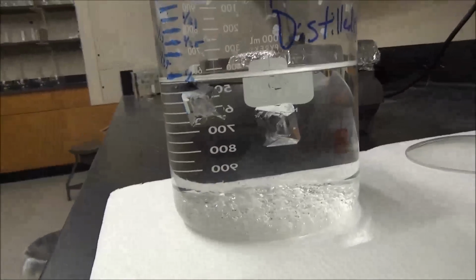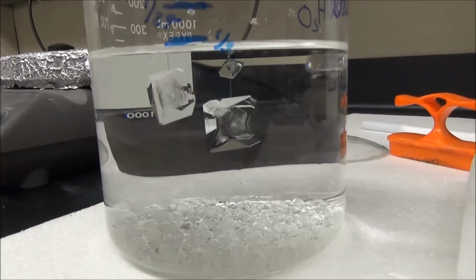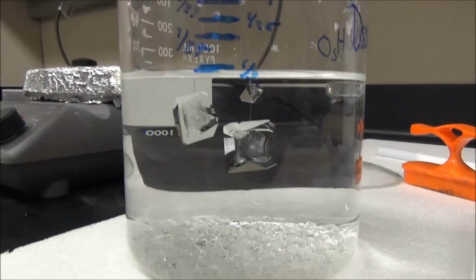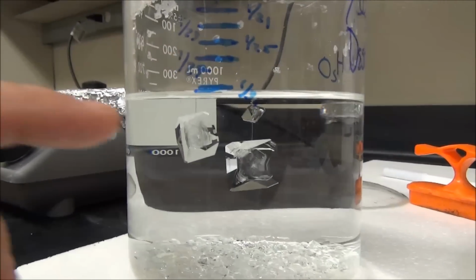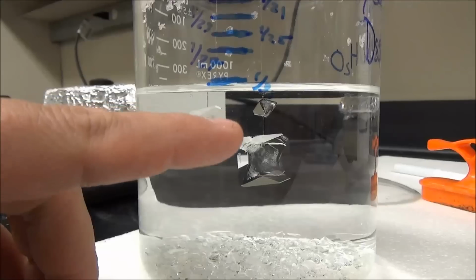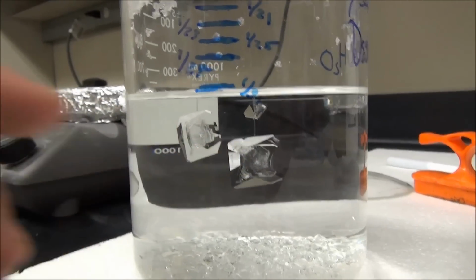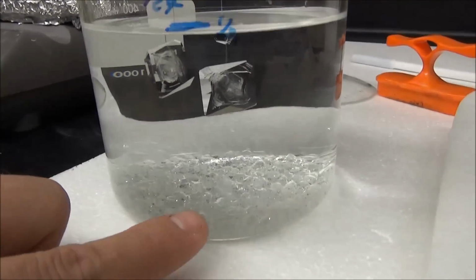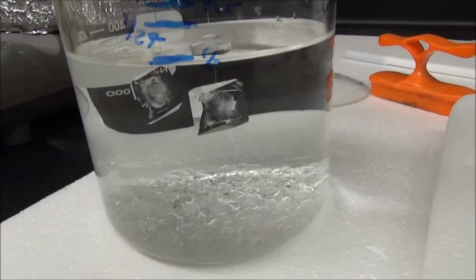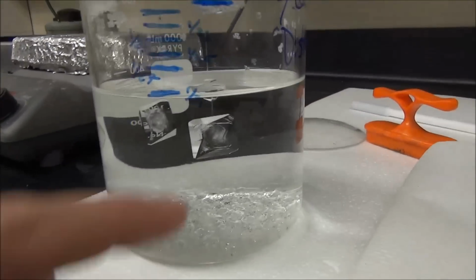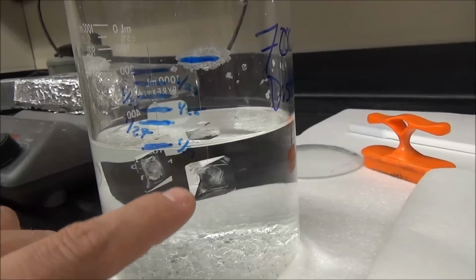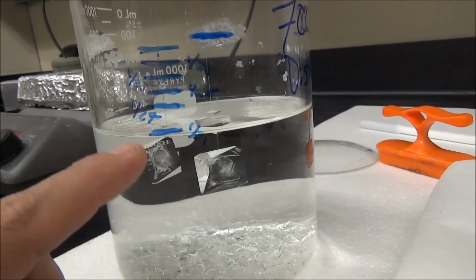Okay, here we are. It's now been 3 weeks since I started this, and I'll let you take a look at the crystals so far. You can see they've grown quite large. But we're about to hit the water line. I could lower them down. We can see that one crystallite is getting closer to the big crystal. But again, we've got a lot of crystalline material at the bottom of the beaker, and all of that is growing, and it's effectively taking away from the maximum size that we could get. Now, this one actually has gotten pretty large.